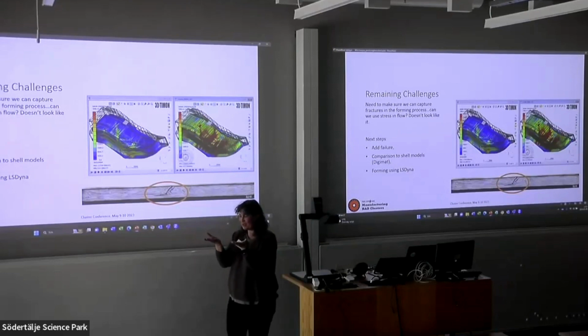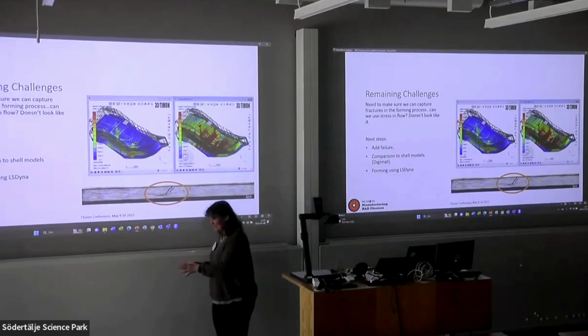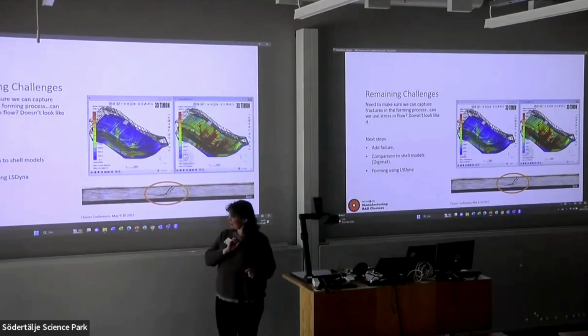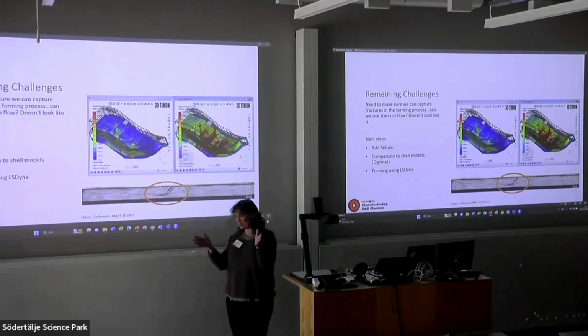So my main objective there was to make sure that what we did in the press was what we were simulating, and that is not as simple as we thought it was. Due to the variations in the material, you cut one layer and then you cut your next layer, and you're creating the stack. Each of the layers has a different grammage, which means a different weight, which means a slightly different size.